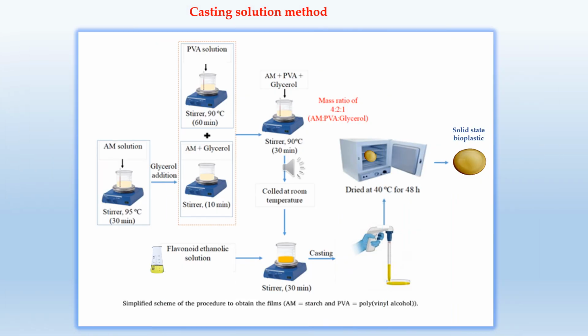The preparation of PVA-based bioplastics functionalized with flavonoids was processed using the casting solution method. In detail, we have prepared two different types of bioplastics starting from PVA in the presence and absence of starch and glycerol. In the first case, the PVA was solubilized in distilled water to obtain a clear PVA solution. At the same time, a stock solution containing starch was prepared and glycerol was solubilized in the starch solution. The starch/glycerol solution was mixed with the PVA solution, resulting in a mass ratio of 4 of starch, 2 of PVA and 1 of glycerol.